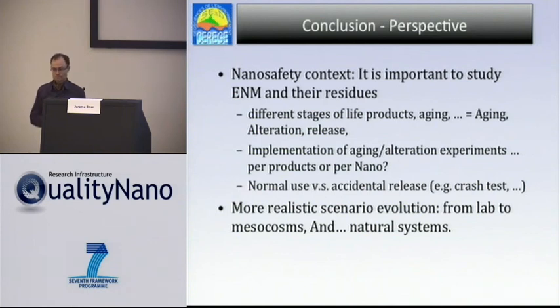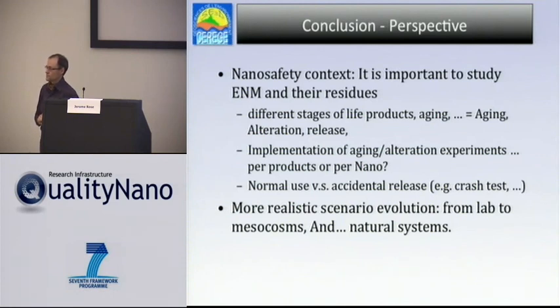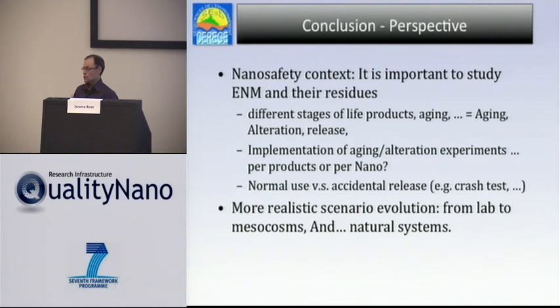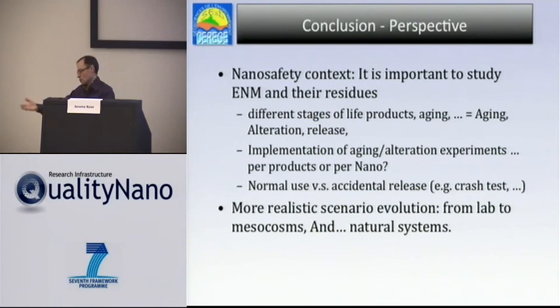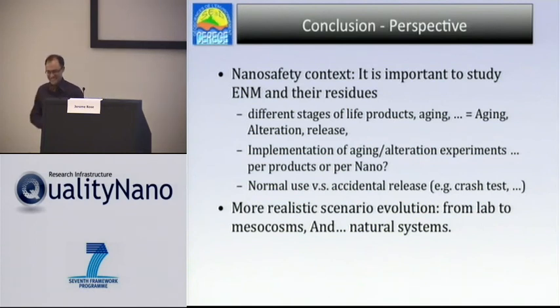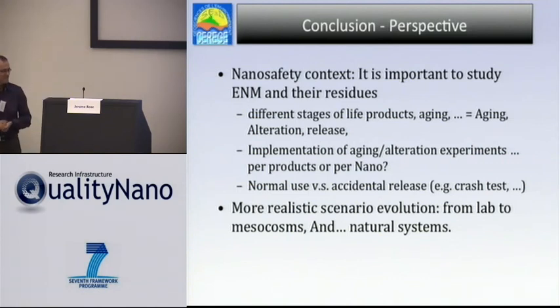With X-ray microscopy, are you also able to identify chemically — is this an X-Radia instrument? You have to use a standard, correct? For the tomography, you're just sensitive to absorbing elements, so you don't know exactly if it's calcium, titanium, or vanadium. That's why we have a combination of platforms — we have tomography, but also 2D chemical mapping where we know from the fluorescence which elements are present. And we also go to synchrotron. Just with one machine is not efficient — it's nice, but not fantastic.